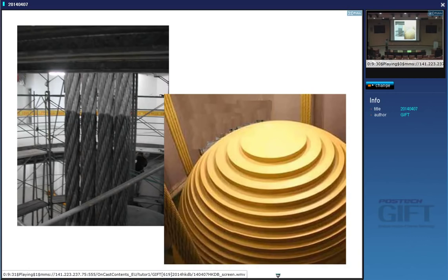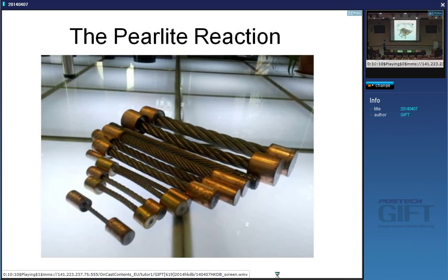And this heavy ball is held by these ropes. Now, what are the ropes made out of? It's obviously steel, but the strongest ropes are made from pearlite, right? So you make pearlite and then you draw it out, and that gives you typically strength of the order of 2 to 3 gigapascals, drawn pearlite. So almost all the wire ropes that you see, like this, are made from pearlite. So pearlite is extremely important in the cold deformed state. It's very, very strong. So these are typical pearlite ropes. You can get them in many dimensions and so forth.